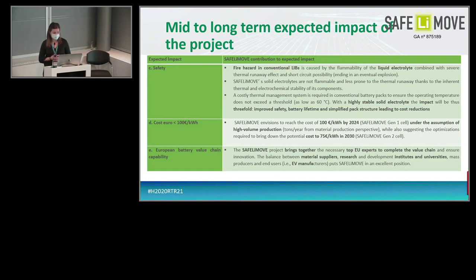So here, usually lithium-ion batteries imply the need of a thermal management system that is costly, as we know, and this is required to make sure that the battery is not going above a low temperature of 60 degrees, mainly because of safety reasons. So if we replace this electrolyte with a highly stable solid electrolyte, this will have a threefold impact. So improve the safety, improve the battery lifetime, and also simplify the pack, implying that we will have a reduced cost.